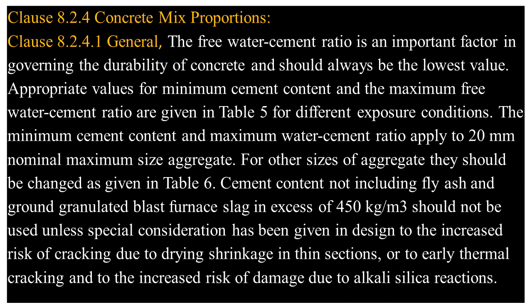8.2.4.1 General. The free water-cement ratio is an important factor in governing the durability of concrete and should always be the lowest value. Appropriate values for minimum cement content and the maximum free water-cement ratio are given in Table 5 for different exposure conditions. The minimum cement content and maximum water-cement ratio apply to 20 mm nominal maximum size aggregate. For other sizes of aggregate they should be changed as given in Table 6.